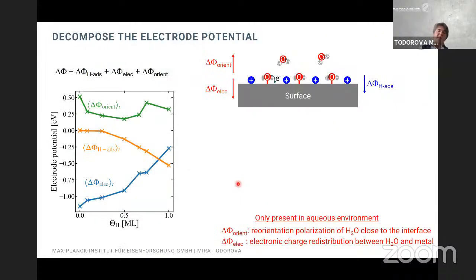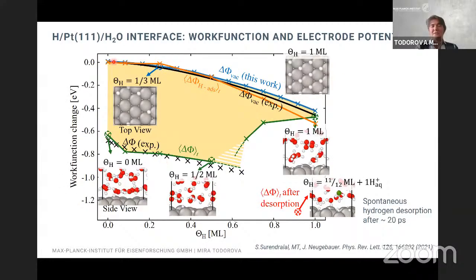Trying to further understand this, we now decompose the electrode potential into various parts. So the one part is related to the adsorption of hydrogen to the surface. So this is a contribution that we have also in the vacuum. And indeed, if we put this curve on top of the previous curves that we calculated from vacuum, you can see that it kind of nicely follows.